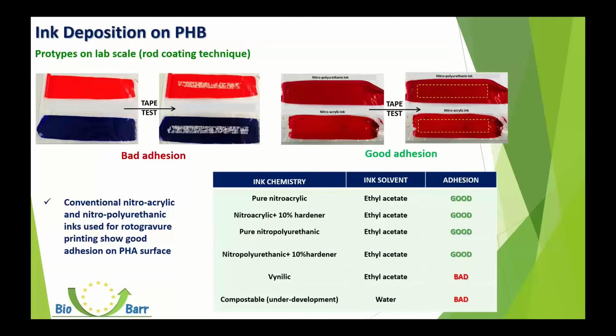Then we also made some tests on the deposition of a compostable under development ink that is a water-based ink for flexo printing. Then after the deposition, we performed the adhesive tape test after 24 hours from the deposition of the ink.